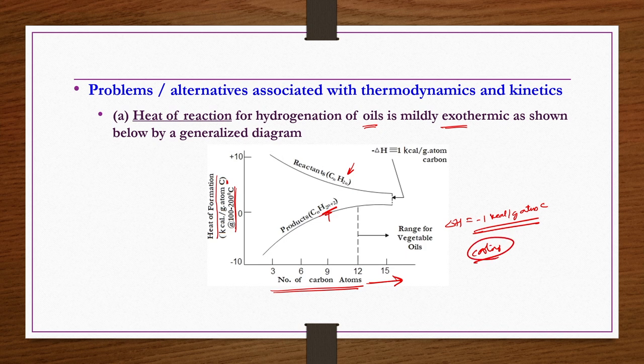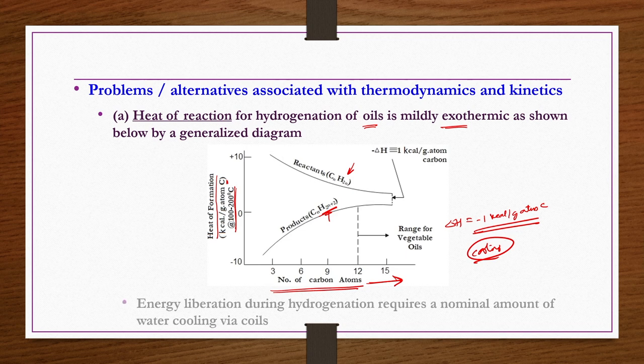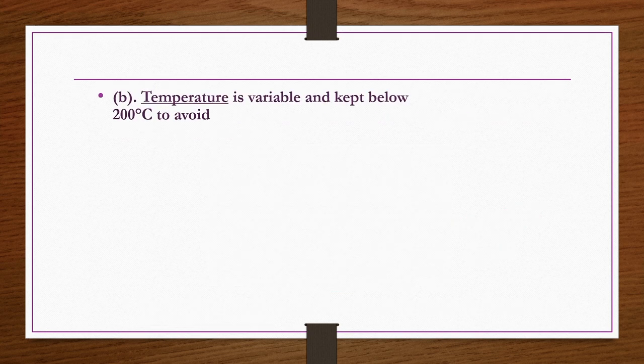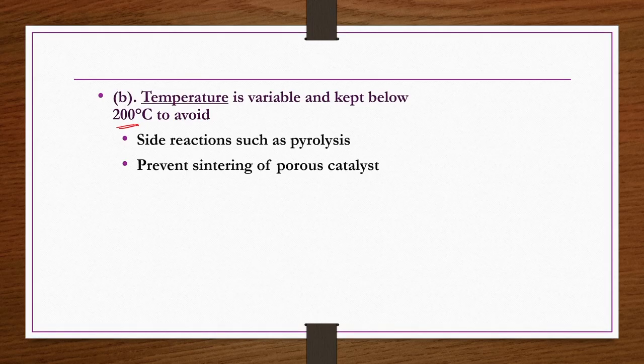or the reactor has to be jacketed so that cooling of the reactor may take place. Energy liberation during hydrogenation requires a nominal amount of water cooling via coils. Coils or jacketed columns are used in general. The next parameter to be considered is the temperature, and it has to be kept below 200 degrees centigrade. Why? Because of the possibility of pyrolysis of oil as well as sintering of the catalyst. Because of these two reasons, the temperature has to be less than 200 degrees centigrade.